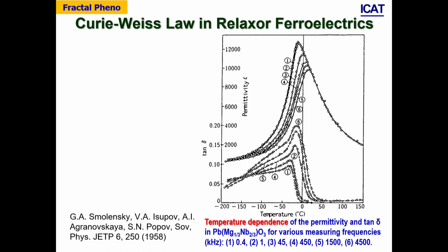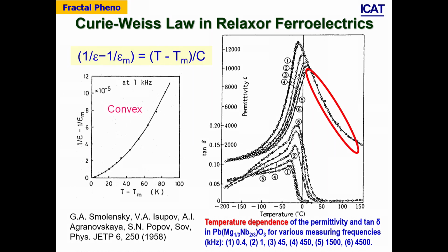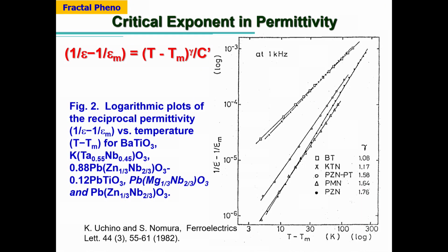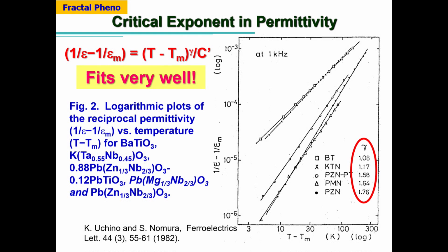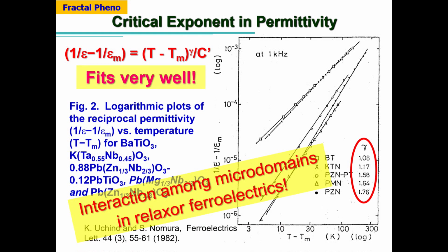So the Curie-Weiss law, again, I'm showing it multiple times here. As I told you, it doesn't really follow the Curie-Weiss law, so it doesn't fit. So we integrate the gamma, in barium titanate and PMN. You can find beautiful linear relations just by changing the gamma values, okay? So this is the temperature dependence, and it fits very well. Interaction among the microdomains in relaxor ferroelectrics may be true.